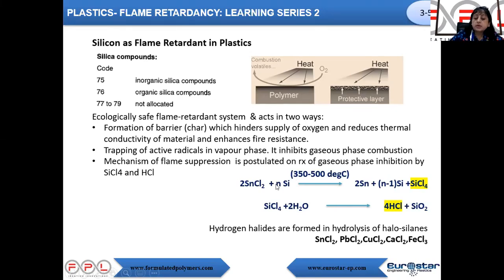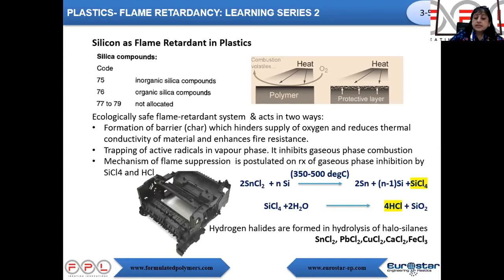You have the silicon and tin chloride at around 350 to 500 degrees centigrade. It results in the formation of a tetrachloro compound. Now this, in the presence of water, gives us HCl. HCl is not so good, but since the dosage is very small, it is comparatively eco-friendly if we compare it with the halogenated materials. So certain halogen halides are used along with the silicon compounds. This is an example of a polycarbonate, glass filled, mineral filled material, and it is based upon the silicon flame retardant system.